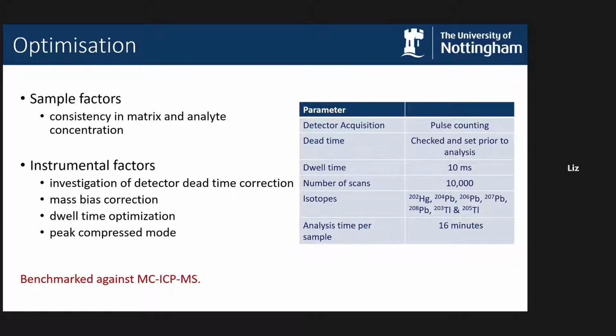Now, the precision of a lead isotopic ratio measurement is generally going to improve with increasing lead concentration because your counting statistics are going to improve. But as I've already alluded to, at high concentrations, there's a danger that the detector on the quadrupole instruments will trip into its analog mode, resulting in non-linearity and the different isotopes being measured in different modes. So we wanted to avoid that happening. So we set out to standardize the lead concentration in all of our samples.